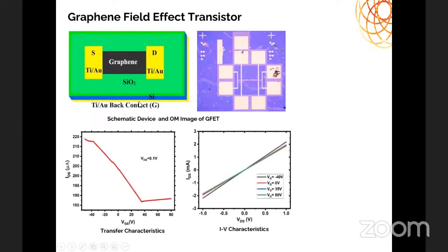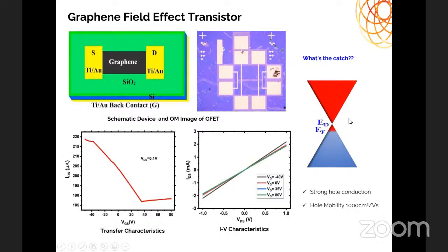When you apply the gate voltage, the carrier concentration in the graphene can be modulated, because the gate can modulate the Fermi level of the graphene, which results in a change in the conductivity and the current value. When you change the gate voltage from negative to positive, the current is reduced, and again it starts to increase at around 35 volts. That means this is not an ideal, pristine graphene, because it's highly doped. Ideal graphene should have a linear ambipolar behavior. This is highly doped graphene. As I mentioned before, the ideal graphene has a Fermi level close to the Dirac point, not below the Dirac point.